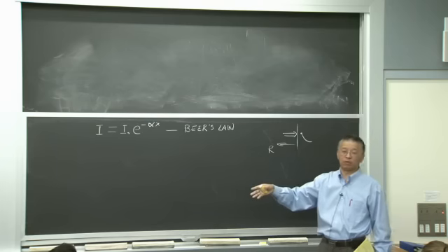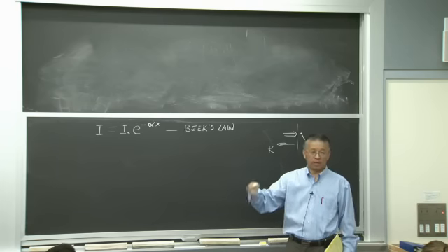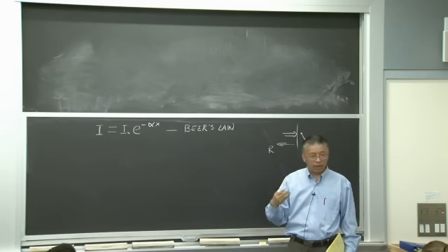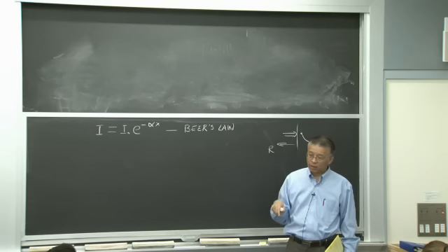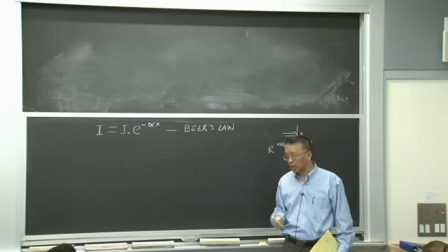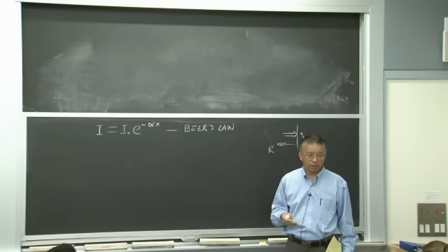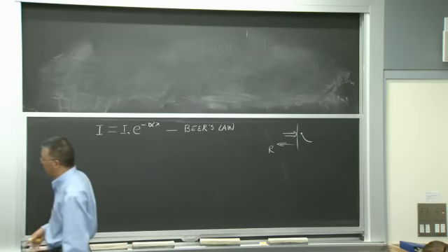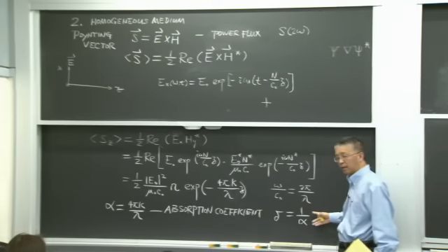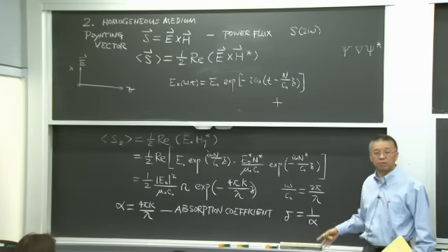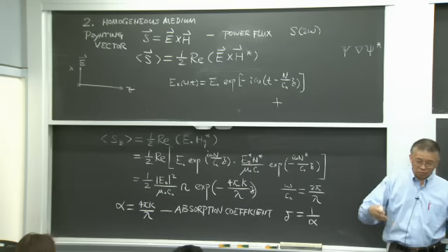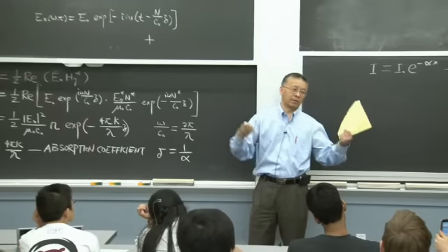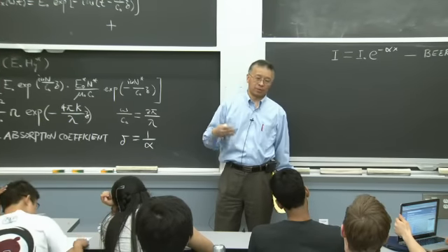In fact, all metals behave that way, right? Metal is very reflective, but the field, maybe 1 or 5% of this wave gets into the metal, and is absorbed typically in 10, 20 nanometers. Okay, but if you have an indirect gap semiconductor like silicon, this penetration depth can be a millimeter. If it is a millimeter, you want to capture that light, so when you make a solar cell, a millimeter means a lot more material, so it's expensive.